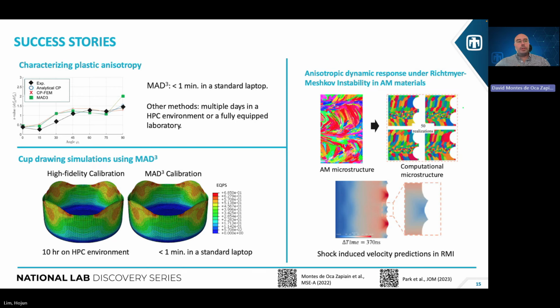For a second success story that we want to highlight, we were able to successfully perform a cup drawing simulation. In this simulation, we used a complex model called Yield 2000 that requires 18 parameters. If you do not have MAD³, you would need to calibrate those 18 parameters doing experiments or running high fidelity simulations on a high performance computing environment.